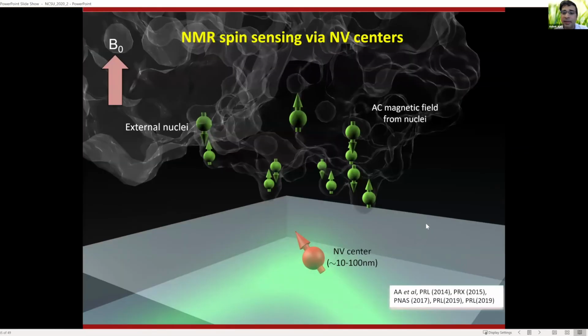So here is an example, and this has become quite popular now in the NV center community. You can use a single NV center close to the surface of diamond, and you can measure nuclear spins in its surroundings. Because these nuclear spins produce a very small but fluctuating magnetic field at a very fixed frequency given by the nuclear Larmor frequency, and because you can read out and prepare these NV center electrons, you can obtain an NMR spectrum of its surrounding environment.